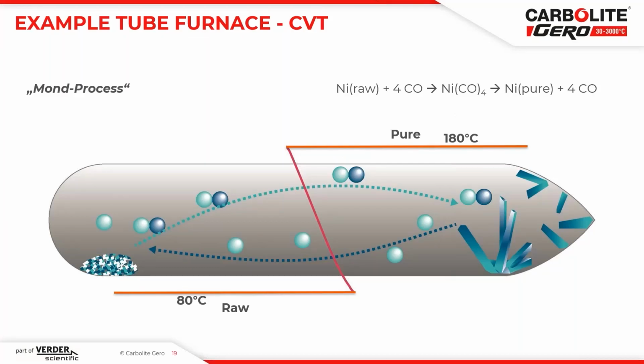Yes, thank you, Tom. So with respect to the step of the Mond process, to make the raw nickel into pure nickel, I have explained before that there are big towers used on an industrial scale. On a smaller scale, so-called ampules are used, and therefore you need a gradient inside the furnace. At lower temperatures, the raw nickel reacts with the carbon monoxide. Then the carbon monoxide becomes gaseous, forming a nickel complex, nickel tetracarbonyl. This nickel tetracarbonyl then circulates inside of this ampule, and at higher temperatures, it decomposes to pure nickel, and the carbon monoxide is expelled.